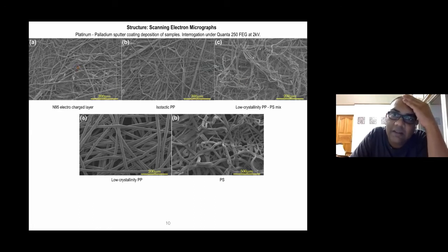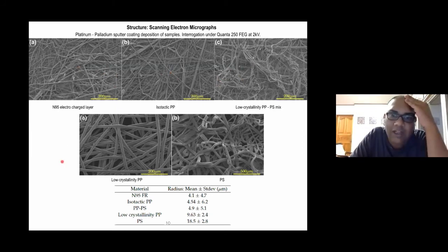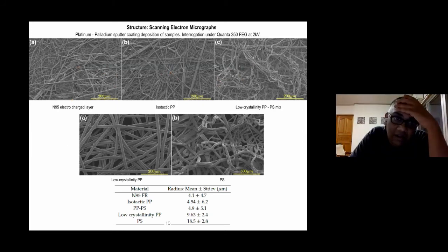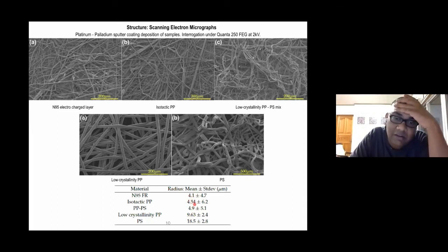I think the difference in the tortuosity of these fibers would impact the porosity, but we will see how that affects it. To give you an idea, since there was a question about the fiber radii, for the commercial N95 layer I got about 4.1 microns mean radius for the fibers. For the isotactic polypropylene it was 4.54. You can see I don't come as low as the N95 mean radius, but it's close enough. So by trial and error, we were able to get close to the N95 quality material.